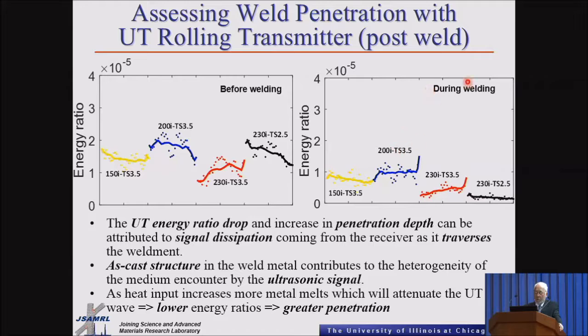But now when we take a look at the energy ratio of the UT signal, you can see when we compare with the plate before welding, there is a drop in the energy ratio. These two have a very similar energy ratio, and we have said those have the same penetration. This other one, which has the highest penetration, shows a big drop in the energy of the UT signal. We explained that probably as you put your signal through the plate, there's some attenuation coming from the heterogeneity of the plate. It could be the microstructure, but in this case we're using a weld metal, which is a cast structure. So as a result, you would expect that to lower the energy ratios.